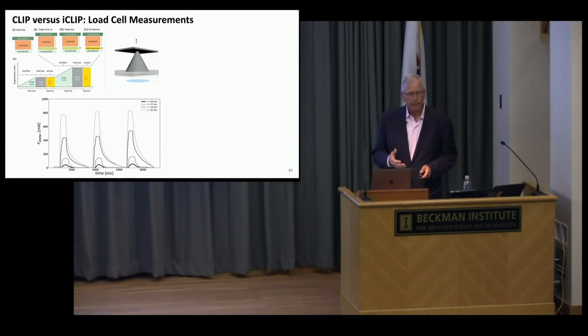What I like to think a lot about is the speed of printing and the liquid adhesion, the Stefan adhesion force. When you have a part in contact with a liquid film between a solid surface and a solid part, it's hard to pull them apart, right? Just think about a drop of water between two plates of glass. That's what we're doing, pulling it apart. And if you put a load cell on the platform and you measure the forces, and you raise the platform up, there's negative pressure created and liquid flows in. So if you have a wide part, you pull the stage up, you stop it, and you watch the fluid flow in. There's a stress relaxation as the liquid goes in and it reaches quiescence. Then you pick the platform up again, another micron or 10 microns, and watch it relax. Well, depending on the diameter of the part, if it's smaller diameter, there's less force or load on this platform.